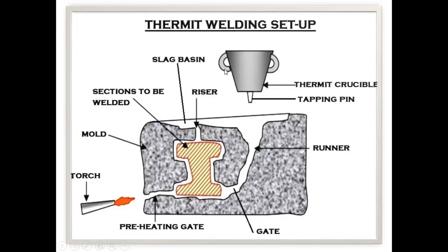So we are trying to give all the channels that are required, as we have seen, starting from the pouring basin, runner, gate, riser, etc. And before that, you have this preheating gate, wherein using a torch, you are trying to preheat the setup, right? So that this molten metal, which is at a very high temperature, if it enters here, there is a temperature gradient, and that would lead to cracking of the base metal. So to avoid that, we are trying to preheat the setup with a preheating gate before the molten metal is poured in.